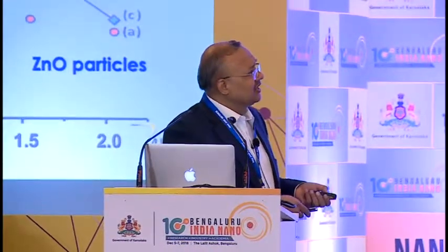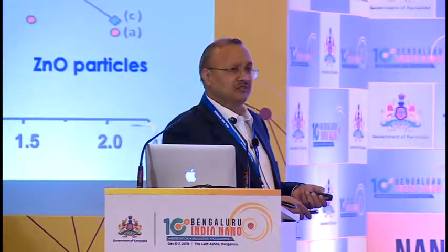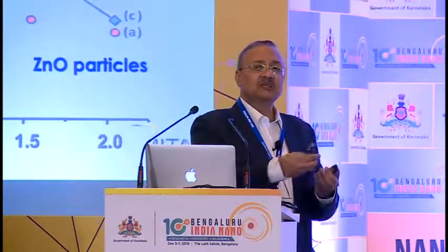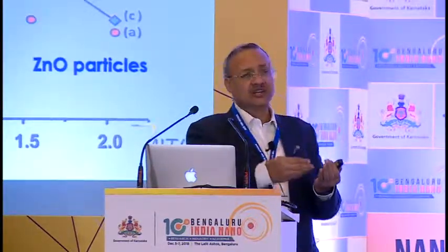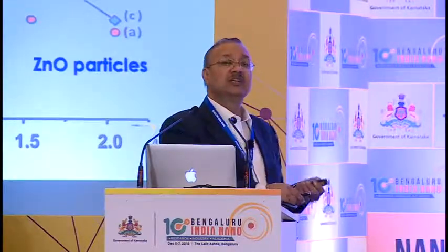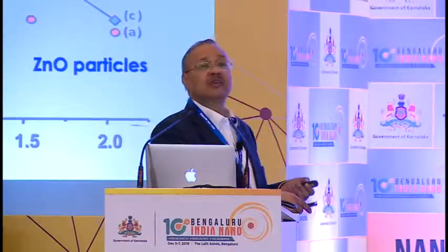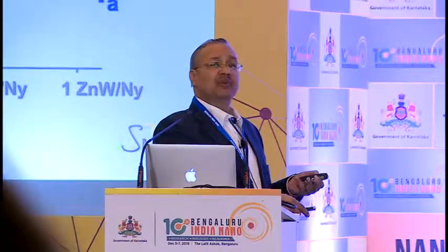And we see the properties of birefringence. Birefringence is the orientation. A fiber is nothing but polymer chains oriented in one direction preferentially. So this preference of orientation keeps on getting higher and higher as we add these materials of high aspect ratios. So what does it do? Nothing happens at the crystalline front. There the orientation remains what it was. But the amorphous region of the fiber just gets up and gets oriented and stays oriented. So this shows that polymer chains are interacting, and the amorphous phase is also acting like a semi-crystalline kind of structure which is more stable. And that brings the change in the properties.